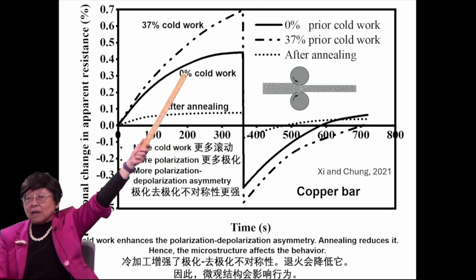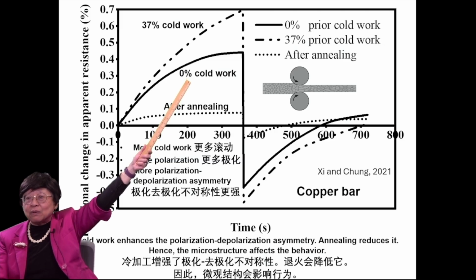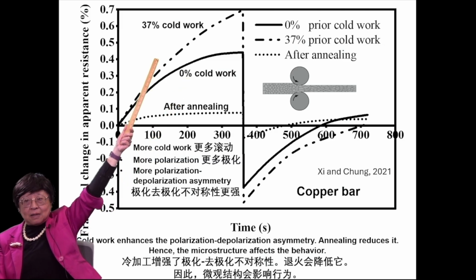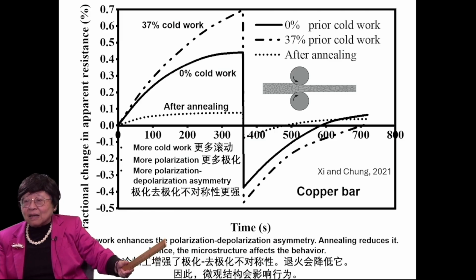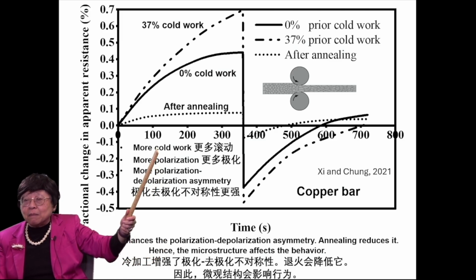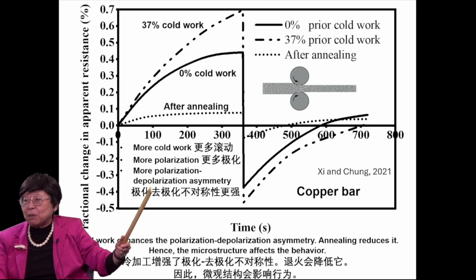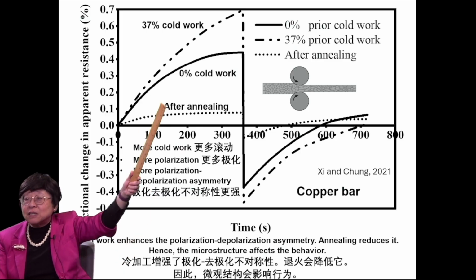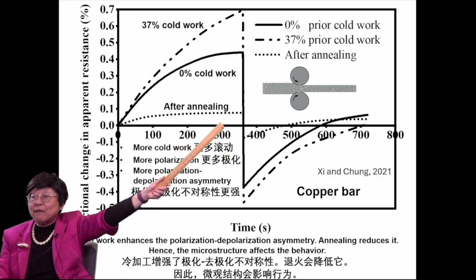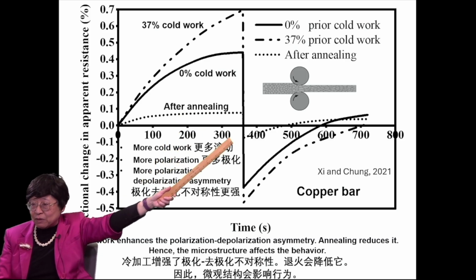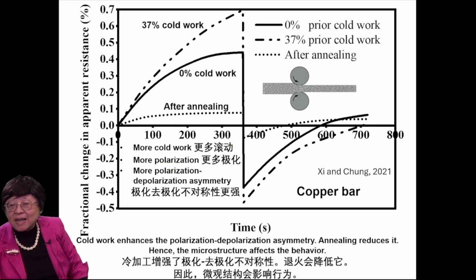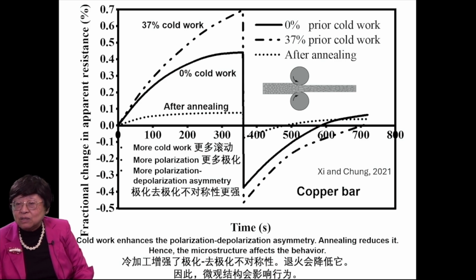I mentioned rolling, and this is copper. It is 0% cold work, that is no rolling, 37% cold work, that's after rolling, and more rolling, that is more cold work, there's higher polarization and also more polarization, depolarization, asymmetry. And after subsequent annealing, it becomes very small polarization, also symmetry. So cold work enhances the polarization, depolarization, asymmetry, whereas annealing reduces it. Hence, the microstructure affects the behavior.